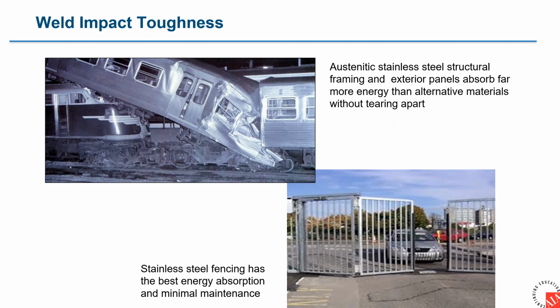Here are some applications where weld impact toughness and the performance of the stainless steel are critical. The passenger rail vehicles globally that are most able to withstand impact, what's standard in the Americas and parts of Asia and some parts of Europe, all have austenitic stainless steels for the outer skin and for the structural framing. They can absorb significantly more energy than the aluminum designs or the carbon steel designs without tearing apart, which is much safer for passengers.